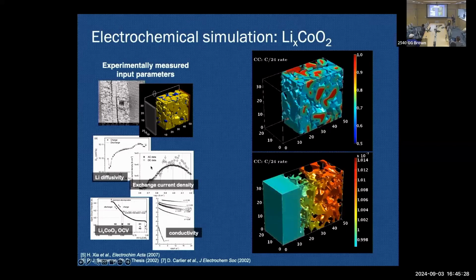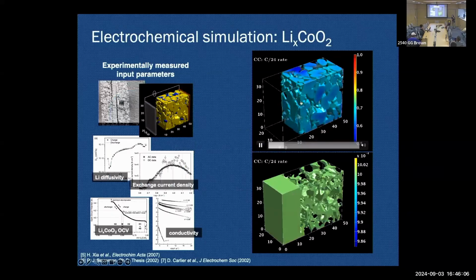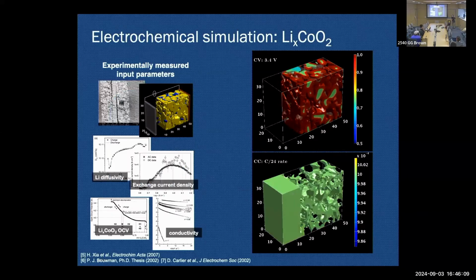Just watching this for a while, there are things you can learn, because those simulations give us a window into the dynamics and behavior of this complex material, and you can really watch it. We learned a couple of things pretty quickly just by watching it. A characteristic scale exists. Delithiation occurs very quickly, and then it gets slow. Maybe I can go back and show you that. You get almost uniform lithiation, and all of a sudden it goes red on the surface. Then same thing, all of a sudden it goes to blue, and then it slows down. So you can catch that.